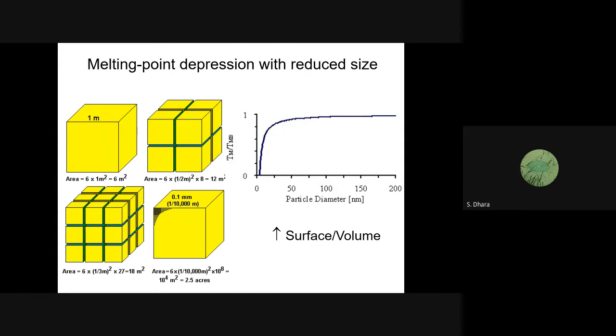Now the question was asked what will happen to this gold, and this has been understood very nicely from a theoretical study and also experimentally: its melting point comes down drastically. You see, the melting point is normalized with the bulk melting point. It is the melting point of the nanoparticle divided by the melting point of the bulk material. If it is normalized to 1, then once the particle size reaches around 25 nanometers or so, there is a drastic drop, and the melting point goes down enormously.